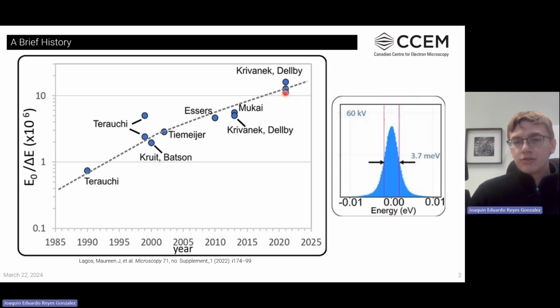This is one of the results that we are able to get on our scope. We're able to get a 3.7 milli-electron volt energy resolution out of it. In fact, we can even push this to about 3.2 milli-electron volts if we fine tune our settings in the microscope. It just takes a bit of more work, so it's not the easiest thing to do. It's taken many decades to get to this point, but now we're at a point to do some very interesting science.